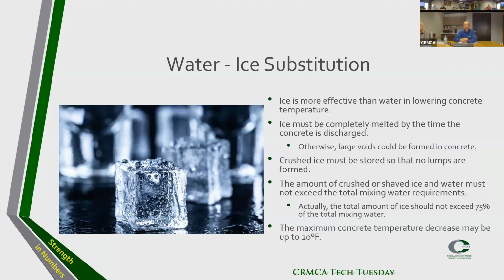Ice is much more effective than water in lowering the temperature. One thing to consider: it must be completely melted once the concrete is discharged from the truck. Otherwise, you're going to have some pretty large voids in the concrete. Generally, the crushed ice must be stored so no lumps are formed. What I've seen before is a big block of ice, and the ice is crushed or shaved right before it gets into the truck. Generally, the amount of ice should not exceed 75% of the total mixing water, and it's obvious that the ice must be included in the total water content. Generally, you can decrease the temperature up to 20 F if you add ice to the concrete.